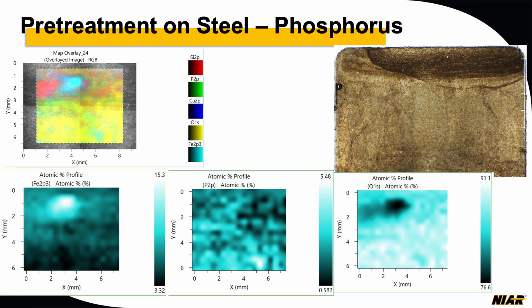So this was showing iron and oxygen. Basically, there is iron oxide focused in that particular spot where there was an error, and then it got a little bit spread out. So we have a little bit of iron spread out, and for phosphate, there is less concentration in that particular area and more phosphate in the other region. There is a combination map that includes all the phosphate, calcium, oxygen, and some silicon. Silicon, I believe, is just a contamination by sample handling. And calcium also might be from one of the processes. So that's the initial analysis of what we have found.